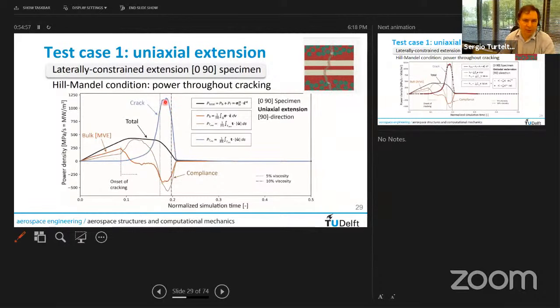If you separate the bulk here from the crack, you get a different story. In fact, you could see that there is an enormous amount of dissipation here on the crack itself. And in the surrounding material, actually, you're storing elastic energy. So that's why it's important to separate the two things. As you pull, you're deforming the bulk material elastically, and the inelastic process is actually occurring at the crack itself. And so we dissect, in a sense, what is the purely fracture process from the elastic deformation in the surrounding material. So the line here in blue is what we should match for the crack.